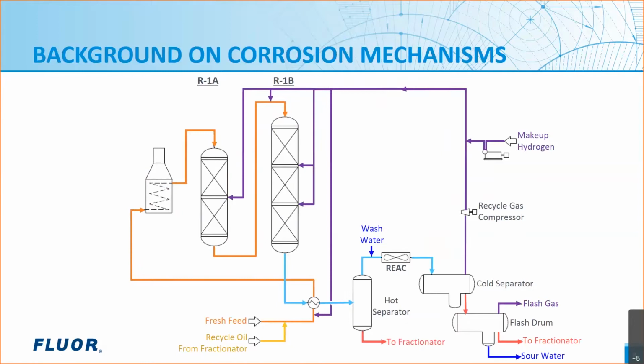Okay, here's another variation of the units. In this unit, the one difference from the previous one is that the reactor effluent now has a hot separator. So after a bit of cooling through shell and tube exchangers, the hot separator might be at about 500 F or so, and that separates out any condensed hydrocarbons, which go out the bottom, versus the vapors, which go out the top.